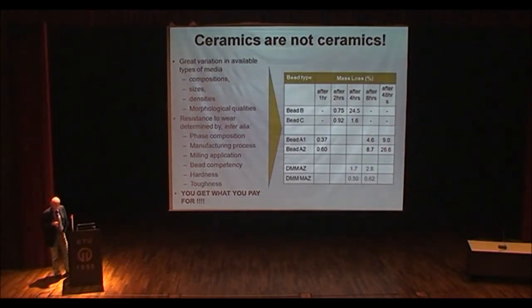And then you go into the really fancy medias where there is zirconia, stabilized ceria, and or yttria. Yttria is the hardest, but it's slightly lighter. Ceria will go up to 6.3, a density, and you're very close to iron at that stage, at 7. There's a trick, I'll come later to the fact with the ceria, but you can have something now, a ceramic bead that has almost the density of steel.